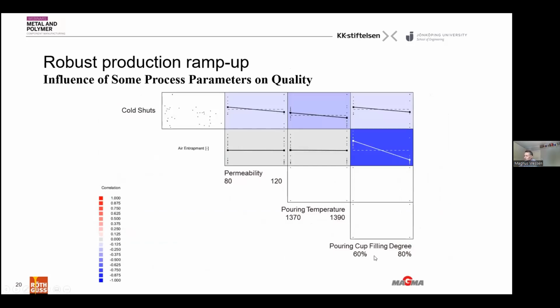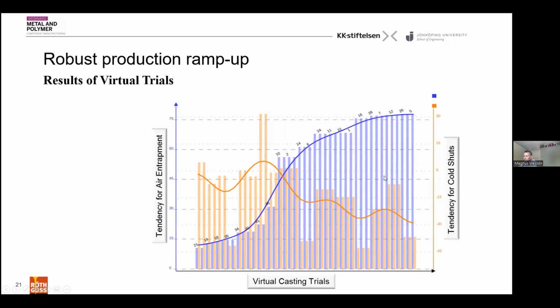But then again, you have this main effect matrix. If you evaluate the air entrapment problems, that's most affected by the pouring cup filling degree, which has the slightly highest impact. If you run with a bad filling degree in your pouring cup, you will probably entrain more air in the melt. You have more swirling in the downsprue. That causes problems in production. So you can then illustrate or analyze the results in many different ways.